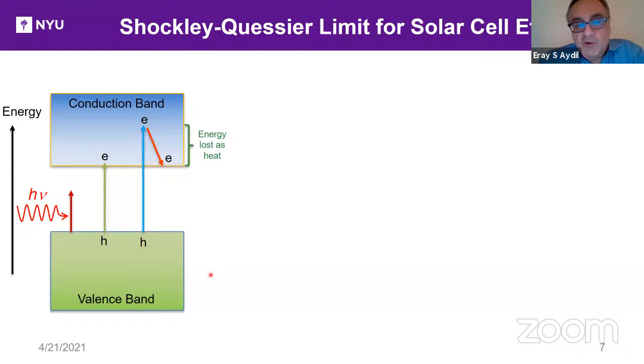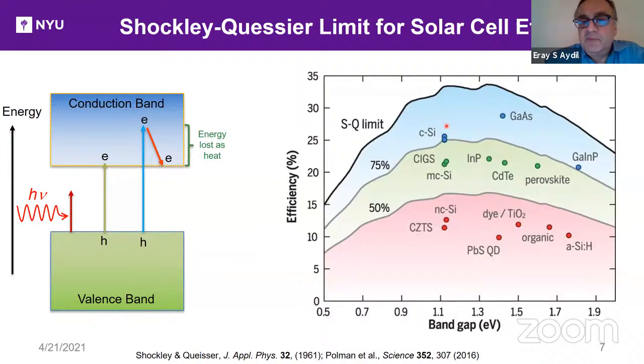So too large of a band gap will throw away too many of the photons. Too small of a band gap will lose too much energy to heat, given a solar spectrum. And there is a happy medium. And that happy medium gives a maximum as a function of the band gap energy. And the happy medium lies actually somewhere around the band gap of crystalline silicon, 1.1 to 1.3 eV. And it's a rather broad maximum. And the maximum is about 33%.